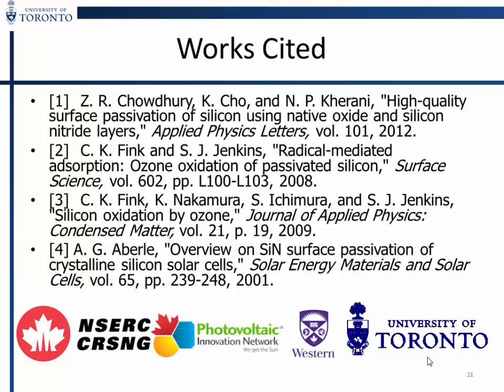Q&A — Question: What is the source of hydrogen used? Answer: The PECVD silicon nitride fabrication process reacts silane with ammonia. Silane has four hydrogens and ammonia has three. All of that hydrogen diffuses into the film. That reaction is why we think you could potentially remove the nitride and just use a hydrogen plasma or ammonia plasma to process these wafers.